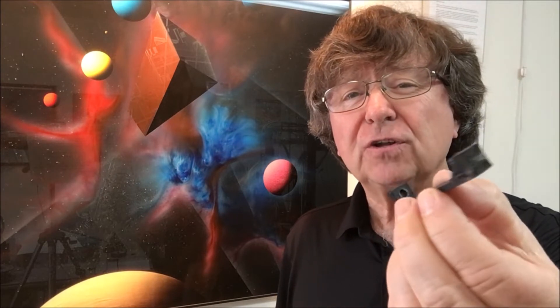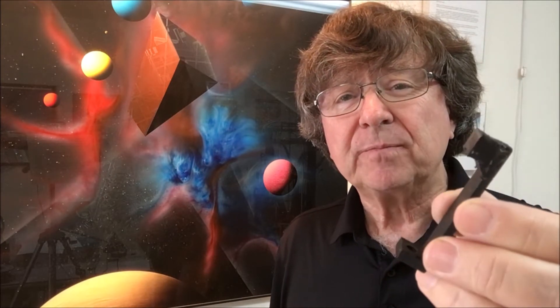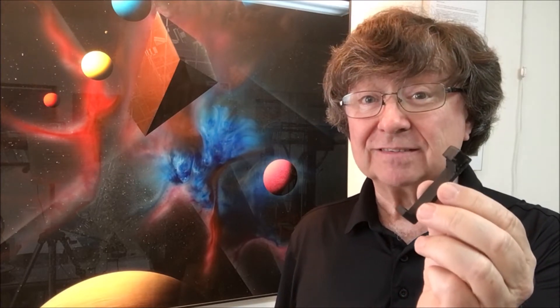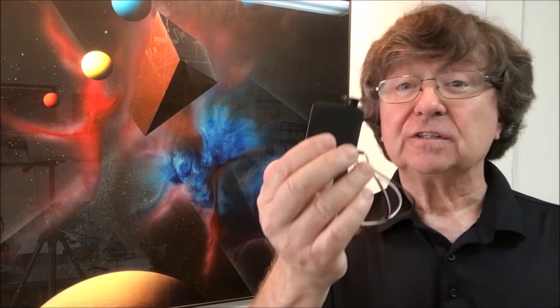This is what the electrode looked like afterwards. About three millimeters of the electrode ablated off during the three second run. Initially, it looks like we'll need to feed the electrodes in at about one millimeter per second. How we'll do that is we'll actually just print gears right on the electrodes, and then we'll use a little servo like this one with a gear on top to feed it into the unit.